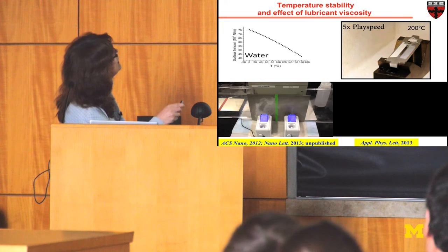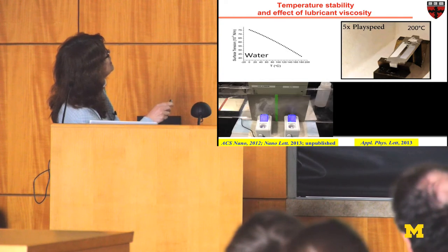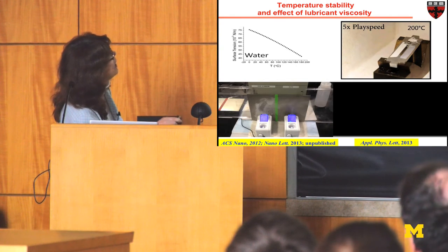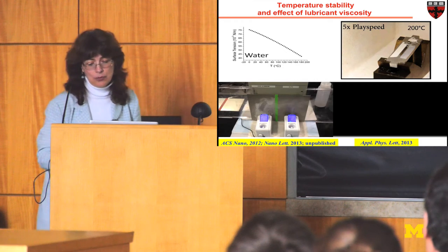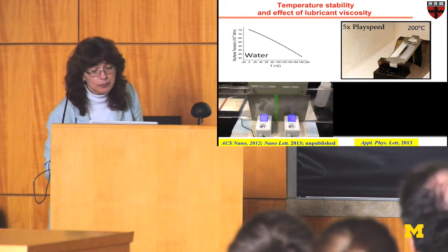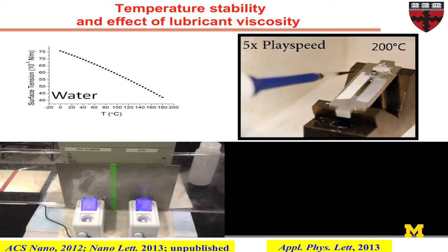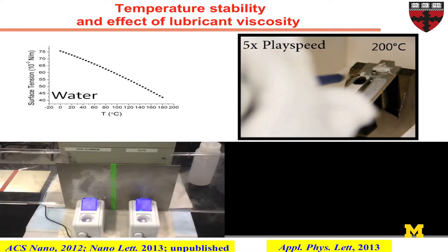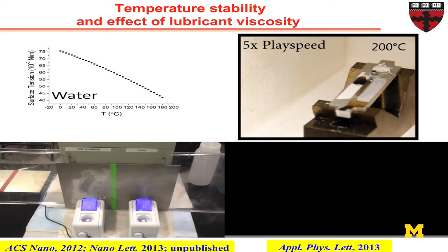So even for water, if you go to high temperatures, the surface tension goes down, reaching the level of organic liquids. But here is the example of a superhydrophobic surface and a slippery surface at 200 degrees C. You can see that the oil is actually boiling, but it provides a nice way to slide on the surface with no contamination. You want to do it at low temperature.